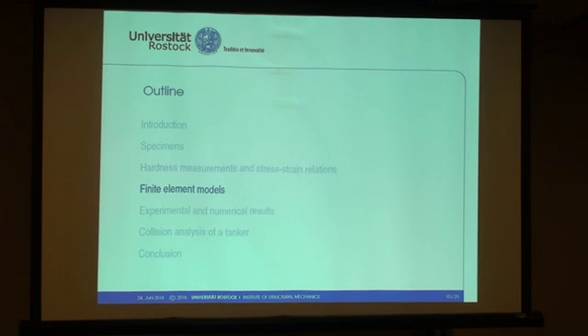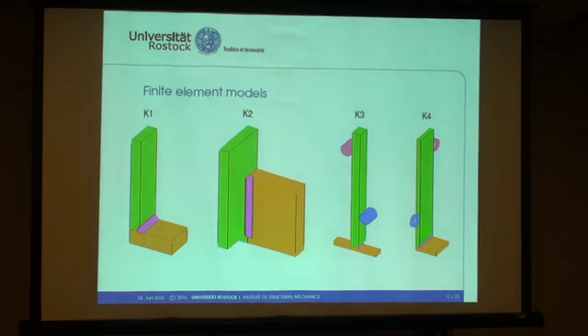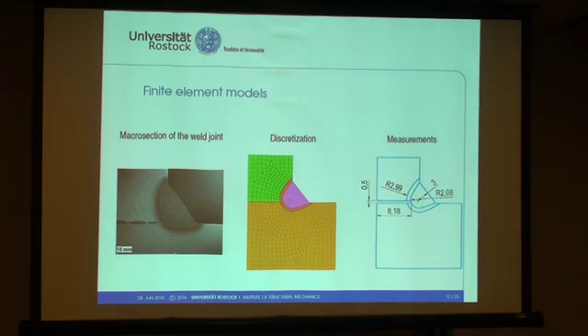The finite element models, all 4 of them: for K1 and K2, I used symmetry in all 3 directions, and for K3 and K4, symmetry in 2 directions. And these are here the bearing and the loading fixture. Those are rigid bodies, discretized with shell elements, and everything else are solid elements. The discretization of the weld joint is determined from this macro section on the left-hand side, and you can see here the weld metal surrounded by the heat affected zone. The different material behavior, the true stress-strain curves I just showed, are applied to both different areas, and an element size of around 0.5 millimeter is used to discretize the weld joint and also the plates near the weld joint.